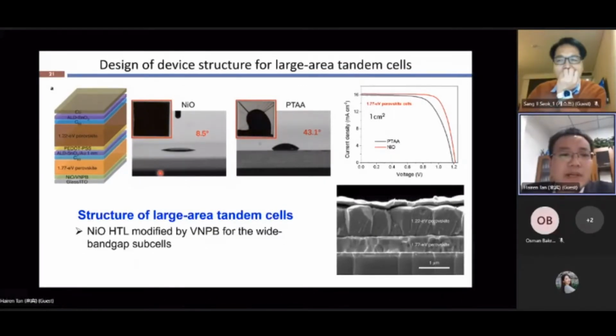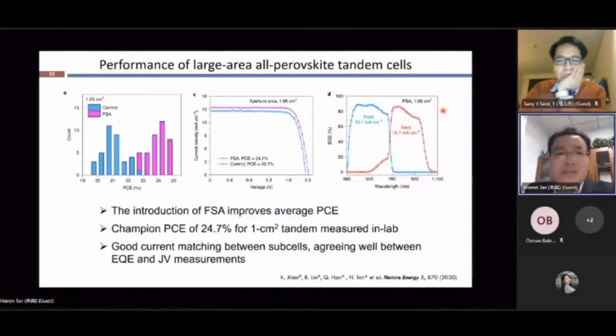And then we thought maybe we can develop a nickel oxide nanocrystal by solution processing. This hole transport layer has very good surface wetting properties, so that would be beneficial for making larger area devices. And to reduce the interface recombination, we also modified the surface of nickel oxide using a cross-linkable small molecule. We call this VNPB. In this way, we can also increase the performance of the wide band gap subcells in the tandem devices.